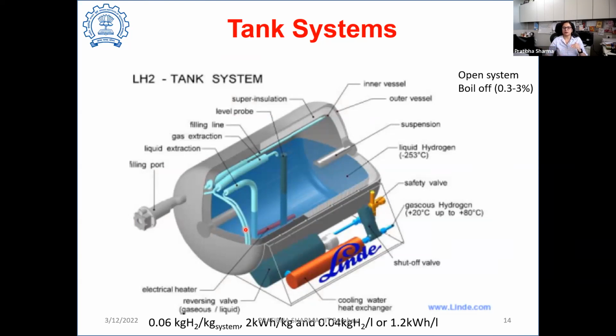That evaporated hydrogen needs to be relieved, that pressure needs to be relieved, else these tanks, which are not meant for high pressure operation but for high insulation, can rupture if the pressure increases beyond a certain limit. So the system always operates as an open system. The amount of hydrogen which evaporates and is left out of the system is a loss, which is known as the boil-off loss.